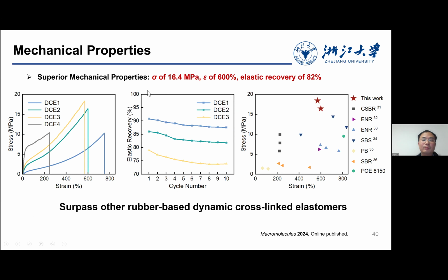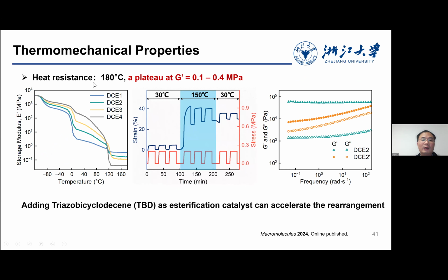And we checked their mechanical properties. We find that the fracture strength can go to 16.4 megapascal, the elongation can go to 600%, and the elastic recovery can approach 80%. If we compare this performance with SBS, the traditional elastomers in the literature, it is better than the reported ones. So in this way, we can achieve a high-performance elastomer just using waste materials or raw materials.